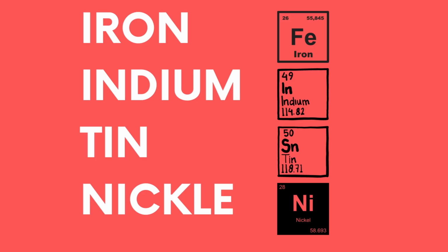The reason why we have a metal oxide layer able to form is because of the presence of a small percentage of base metals like iron, indium, tin, and nickel. Something to note, particularly with nickel, I have heard of a lot of patients having issues with allergies around this. You get women, for example, who say that they can't wear those store-bought earrings, the cheap earrings. They have to wear precious metals, gold, pure sterling silver. If they have issues like that, it's a pretty good sign that they may end up having troubles with base metal alloys in the mouth. Not that I use metals very often, but that is something to bear in mind. Look at us, fun facts galore.